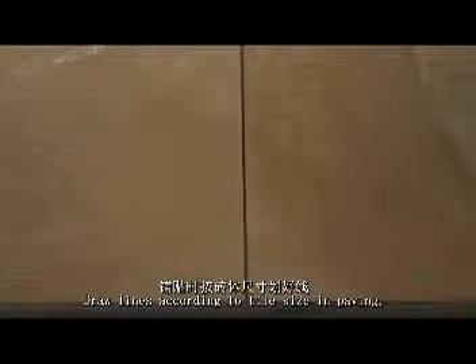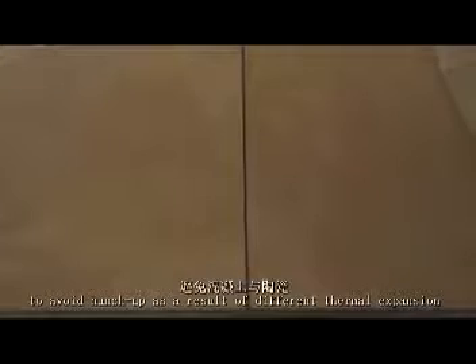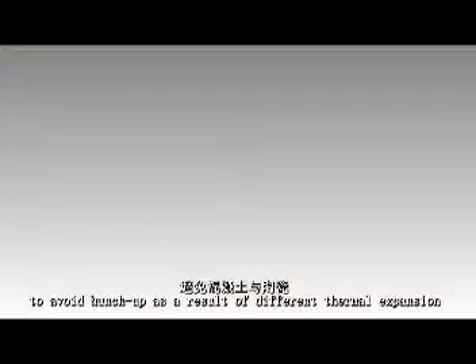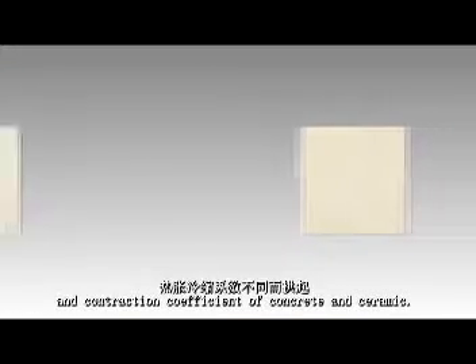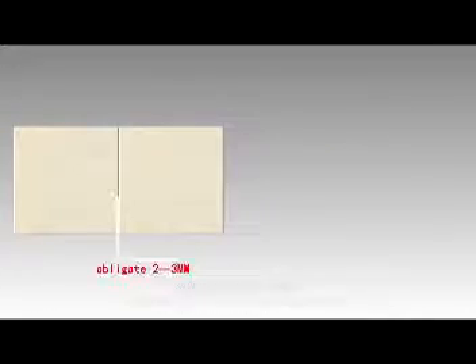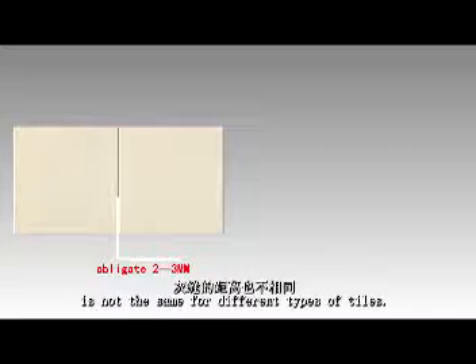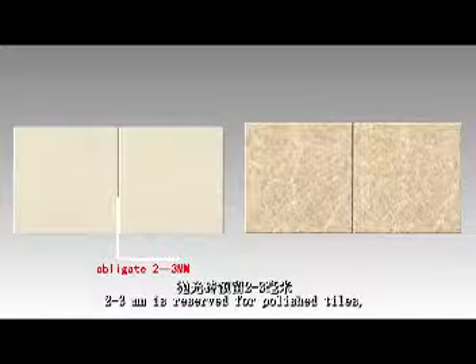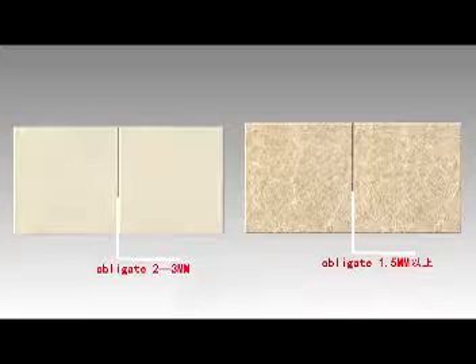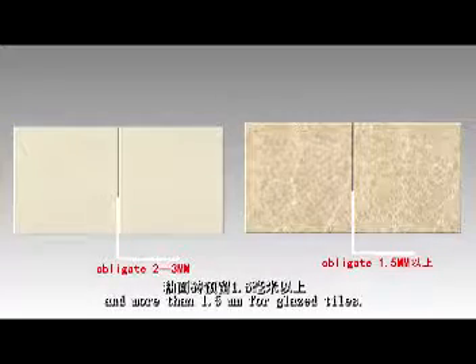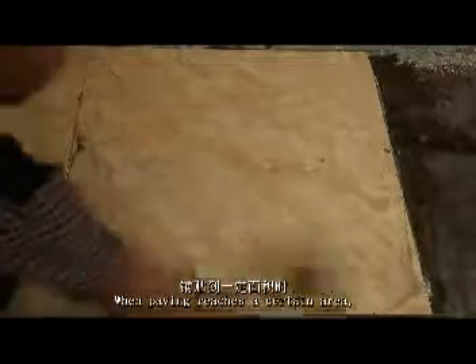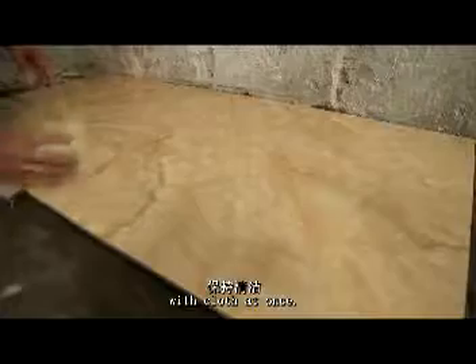Draw lines according to tile size in paving and set aside gray seam to avoid hunch-up as a result of different thermal expansion and contraction coefficient of concrete and ceramic. The distance of gray seam is not the same for different types of tiles. 2 to 3 millimeters is reserved for polishing tiles and more than 1.5 millimeters for glazed tiles. When paving reaches a certain area, wipe residual contaminants on the surface of tile with cloth at once.